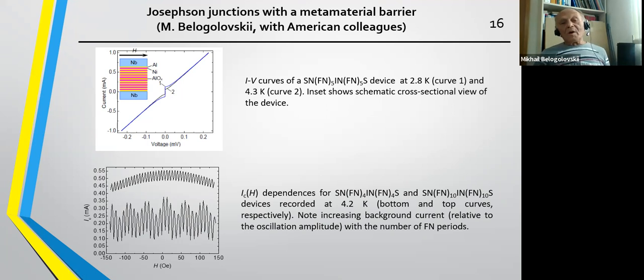What does it mean, and how to understand what happens if you replace a trivial aluminum oxide, or maybe a trivial aluminum or nickel-aluminum weak link, with such a multilayer? It is difficult to answer this question. In our paper that was published in Physical Review Applied, a quantum explanation was proposed. So imagine that you compare the situation in the central part of this device and near the edges. In the central part, you have the shortest way from one electrode to another. But the structure, of course, is strongly disordered, since a layer thickness of 1, 2 nanometers means that it is not a good film, but rather a conglomerate of different grains.